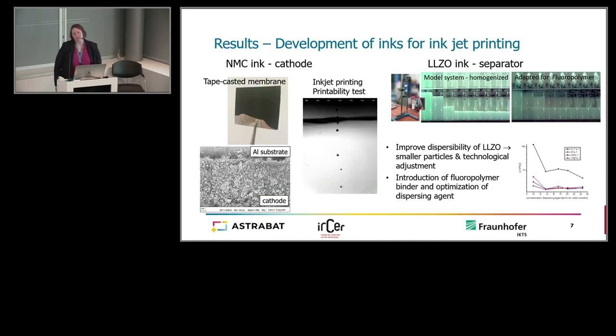I mentioned that we were looking at additional architectures in the pre-prototype phase using alternative production methods. So here we're working on the formulation of inks for inkjet printing. Our 2 partners, irCer and IKTS at Fraunhofer, are looking at the formulation of the NMC ink and the LLZO ink, with the idea basically of printing different structural components to improve the performance, particularly the power performance. So you can see from the inkjet printability test that we have developed a printable ink, and at the moment we're working on adapting the inks to contain, for example, the fluoropolymer binder for the cathode side.